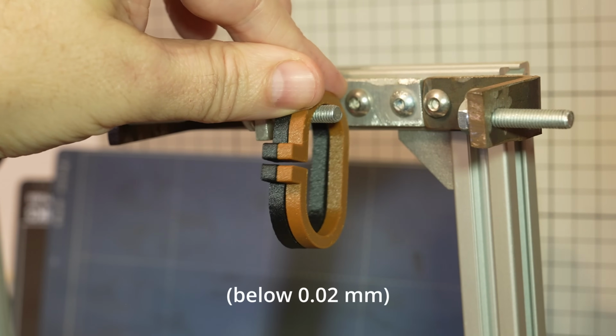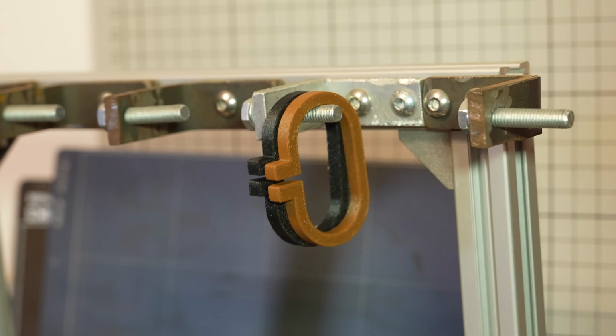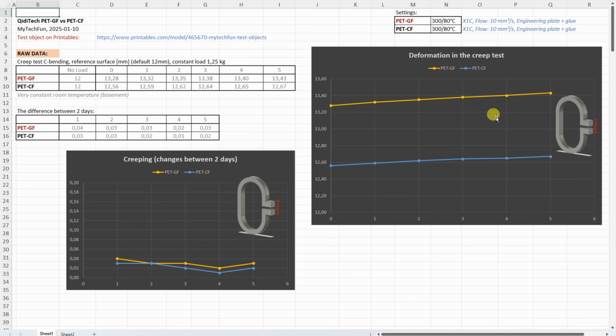13.43. Visually the permanent deformation looks equal. In both cases they resist creeping very well. This is a directly measured value, between two reference surfaces, and smaller values are better, this means less deformation. But with the creeping, the difference between 2 days is more important, and that's what we can see on this graph. And in both cases these are extremely small values. This small wave is actually inaccurate in the measuring, but in both cases they resist creeping very well.